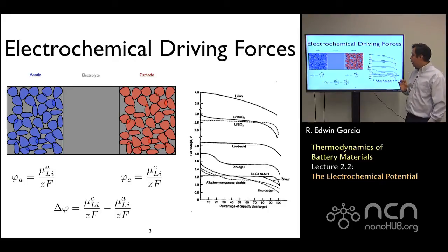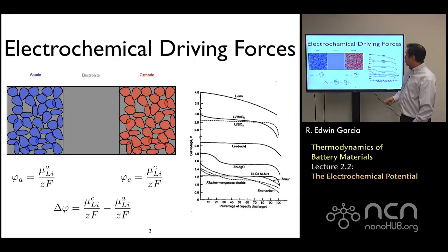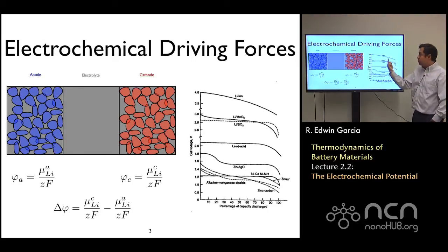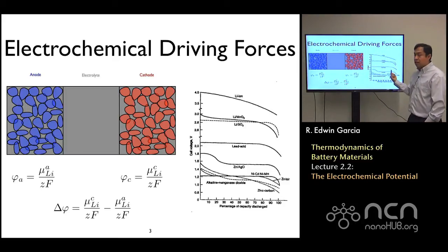From the point of view of designing a battery, what you really would like is this potential to be as high up as possible, okay? Or if you prefer, that chemical potential difference with respect to the reference to be as large as possible, and you will also want that the width of that regime, the concentration regime, will be also as wide as possible. Basically, by understanding the origins, by looking at how that chemical potential is specified, we should be able to maximize the voltage and the concentration, the solubility limit that material can deliver.